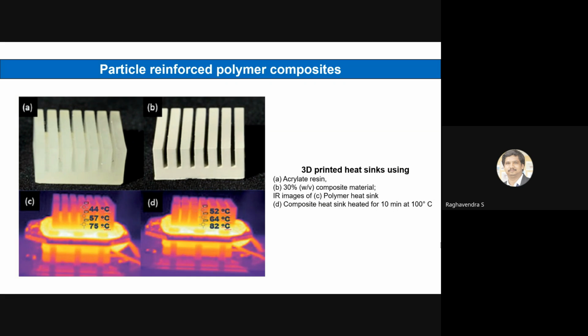This is one example you can see. One of the researchers, I think in 2016, 3D printed a heat sink. The first picture, A, is acrylate resin, and the second one, B, is a 30% by weight composite material. The particles they added are micro diamond particles in acrylate resin. What is the enhancement they got? You can see in pictures C and D. If you heat both of the components at the same temperature, that is for 10 minutes at 100 degrees Celsius, you can see the difference here: 75, 57, 44, that gradient is there. But with the composite material, it is 82, 64 and 52 degrees Celsius. So there is an improved heat transfer rate by the addition of diamond particles. This is one classic example.